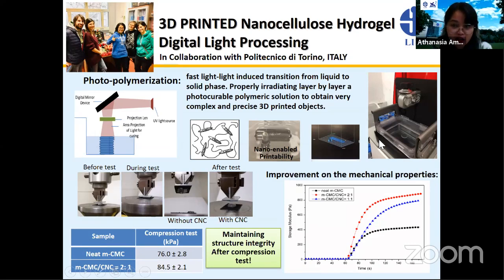When we incorporate the nanocellulose into these 3D printed hydrogels, as you can see, we did a simple mechanical compression test. In the full compression test, the system without the CNC, the hydrogel gets scrambled up into pieces. While when we incorporate the nanocellulose, after the full compression test, it maintains its structural integrity. You can also see from the rheology properties that it induces double the storage modulus when we introduce the nanocellulose. Currently there is a master's student at Politecnico di Torino who will continue our interesting results.